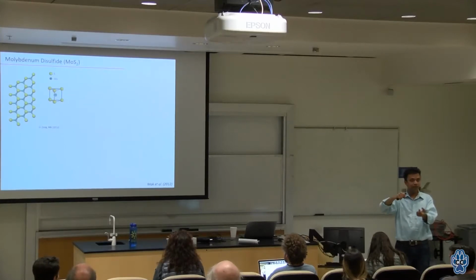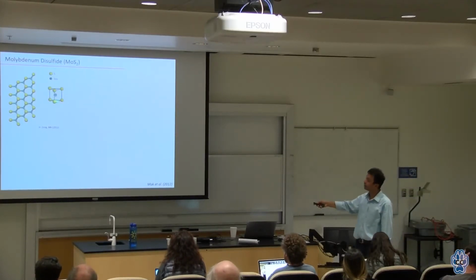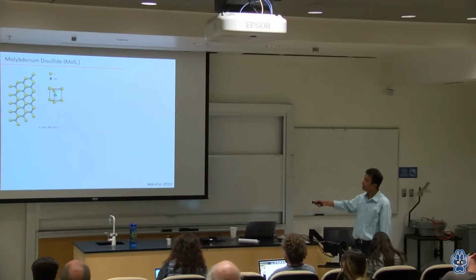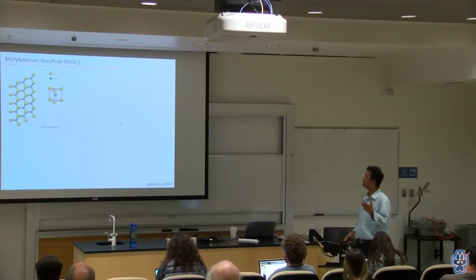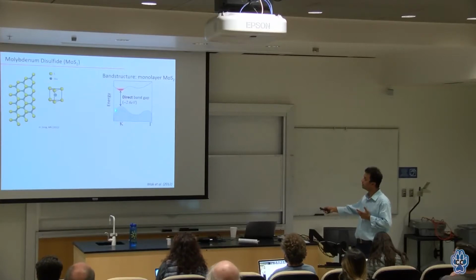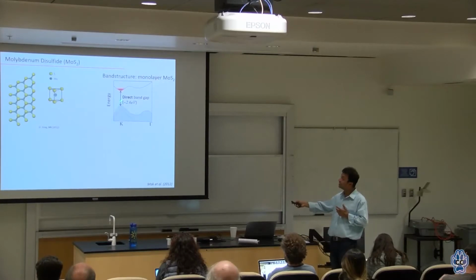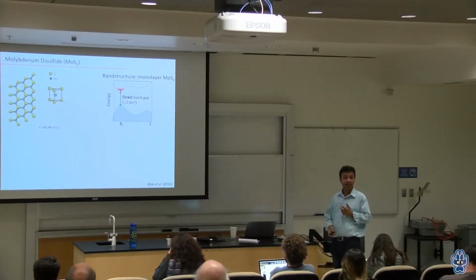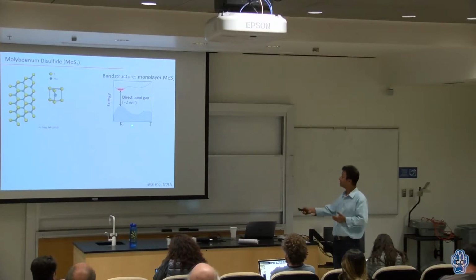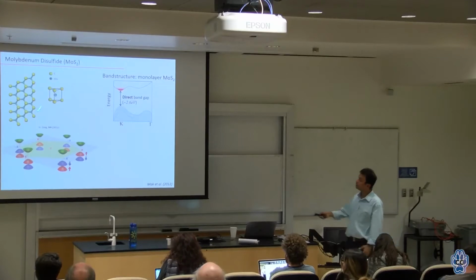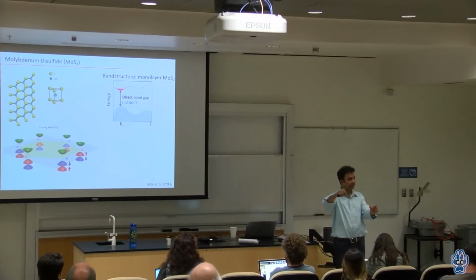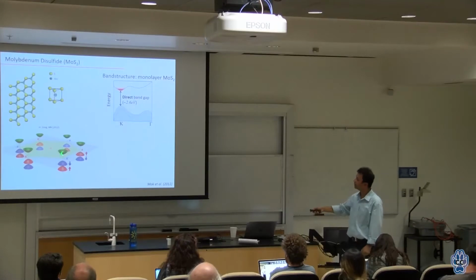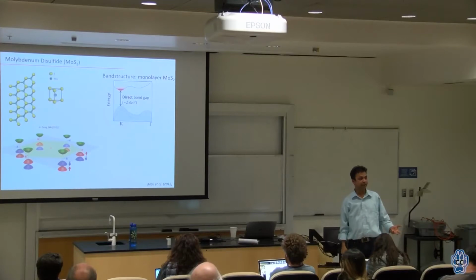So this is molybdenum disulfide, where you have a molybdenum in the middle and sulfur on the outside. They call it a trigonal cell, and it has some crystal symmetry. Because of the crystal symmetry, this is what the band gap looks like for a monolayer. You can see, indeed, this is a direct band gap semiconductor at the monolayer level, at the K point. Because it's also hexagonal, you will have this band at six different points in the hexagon.